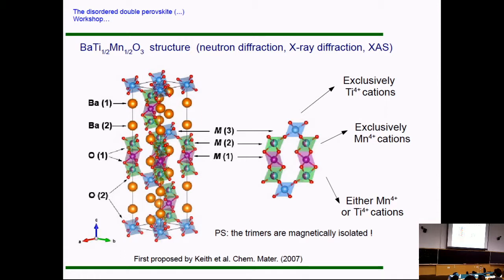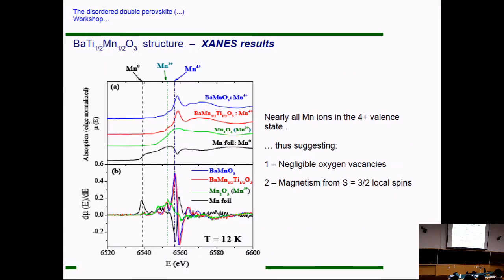I will now resort to some experimental results trying to support this scenario. The first thing I do is try to verify the valence. For that, we simply do XAS, X-ray absorption. And here you can see how the spectrum for our compound nicely correlates with the spectrum for the standard for manganese 4+, and here the comparison with some other valence. So I think that, in terms of our sample, this goes down to say that we have negligible oxygen vacancies, because otherwise we would have charge distribution, and then you could have some sort of mixed valence. And we have as well that this is a spin 3/2 system, right? We have local moments S equal 3/2. So this is the first message we got.